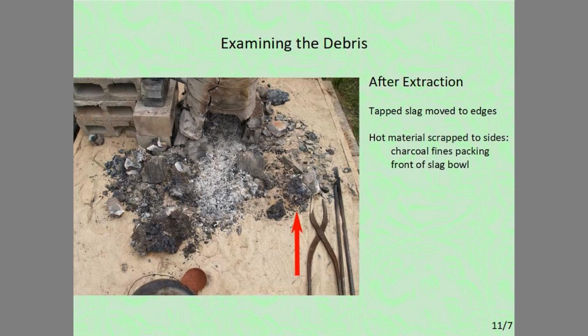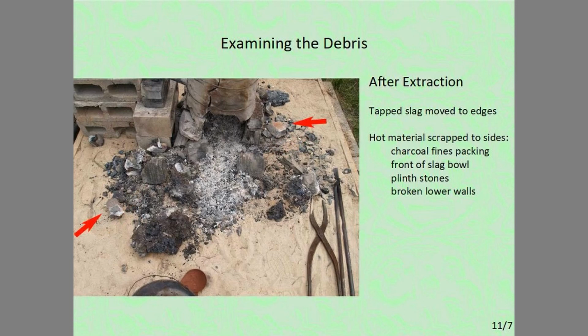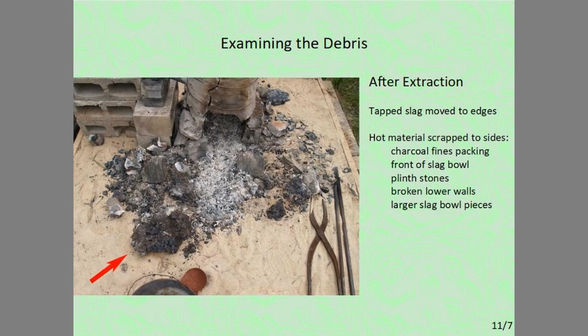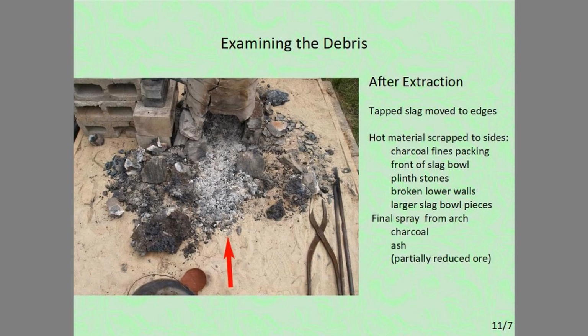Pieces of the slag bowl will be broken away to expose the bloom. Several of the base plinth stones had been removed to create a larger working space. It's not unusual to break away several pieces of the lower furnace wall. These may be partially baked into a rough ceramic. Sometimes pulling the bloom clear will also pull free the remaining slag bowl, which means large pieces of this may be found. A spray of fine ash, partially consumed charcoal, can be expected in a fan shape from the mouth of the furnace.